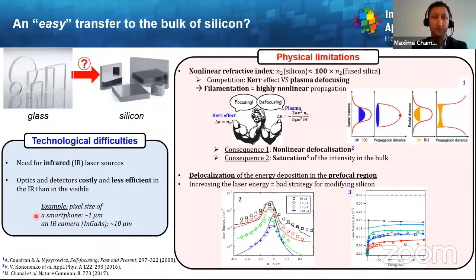For instance, your smartphone has roughly a pixel size of 1 micron, while a very good IR camera in indium gallium arsenide is around 10 micron pixel pitch. But if this was the only reason, then it would be possible to functionalize silicon with a laser. No, the main problem originates from physical limitations, especially when you look at the nonlinear refractive index of silicon.